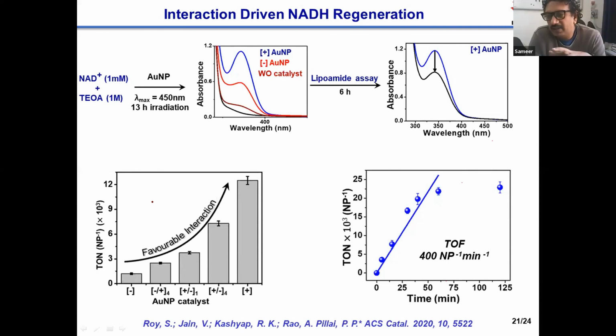A related question: would it depend on per nanoparticle or per ligand? Here we have calculated with respect to nanoparticle, but you are right, we can also estimate it with respect to ligand because we know the number of ligands. For example, the size that we are working with is something like 10 nanometers, so there will be something like 600 to 700 ligands on the surface, or I would say 500. I will not go to 600. I think 500 is a decent number. So I can convert it into per ligand as well. But the catalyst here is the nanoparticle, and that is why we represent it in terms of nanoparticle.